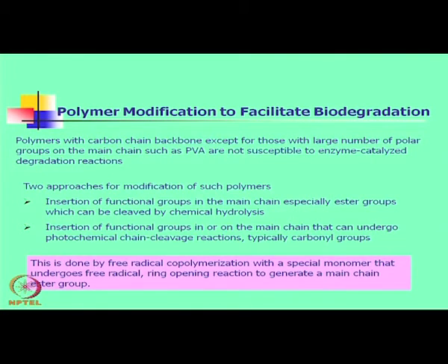But if the surface of such LDPE films can be made polar, by oxygenation, that is, oxidized by some means, so that some oxygenated groups like OH group, ketonic group, ether group or ester group are created on the surface of this LDPE by oxidation, then such LDPE can be degraded by microorganisms. So, that is a kind of modification.